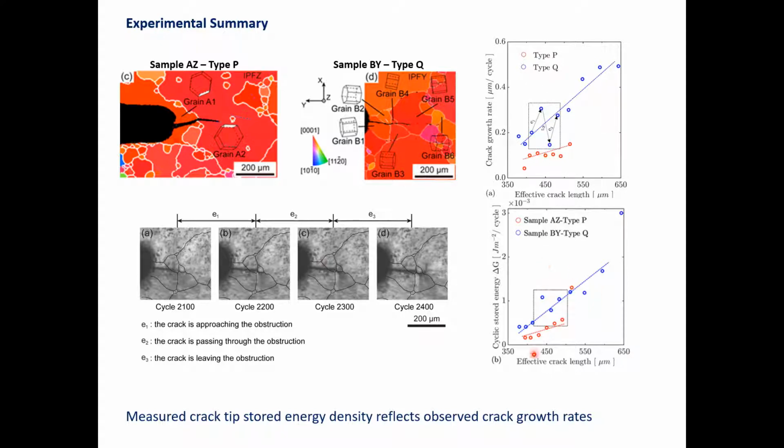And in addition to which, what's quite nice is that the stored energy density also picks up some of the variation we can see here taking place and observed in the crack growth data. And this is something we're very definitely interested in and following up with higher resolution where we can to try and understand more.